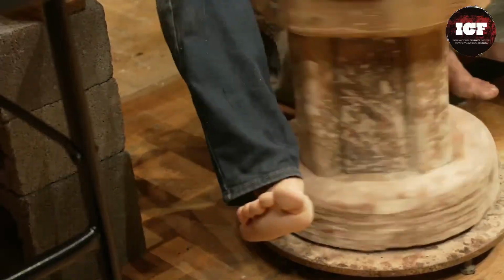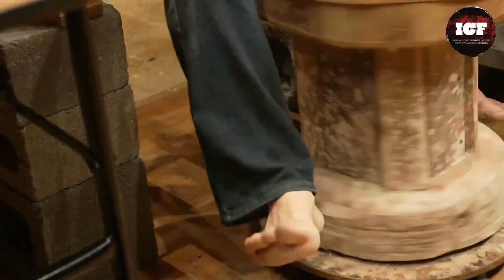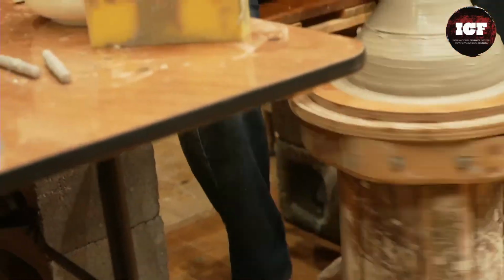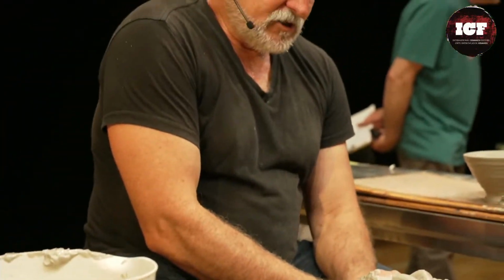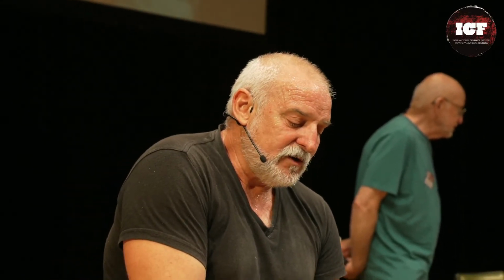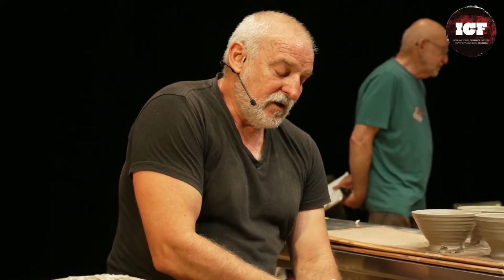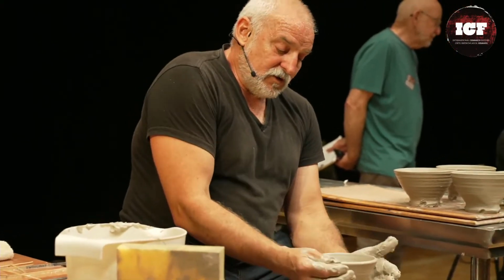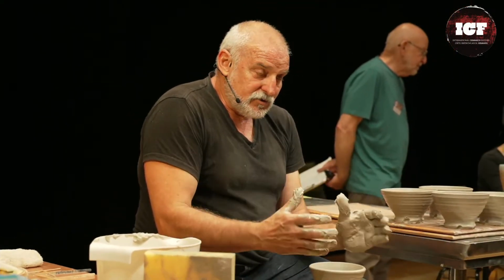Also, I reduce while I'm cooling. I crash cool down to 1100 after I finish the firing so that I don't get cristobalite forming in the liquid silica. But then I put an extra stoke of wood into the firebox to allow it to reduce cool.